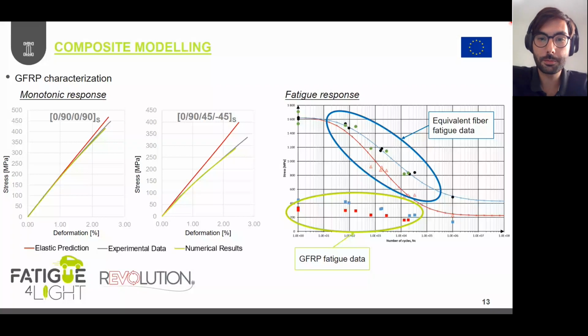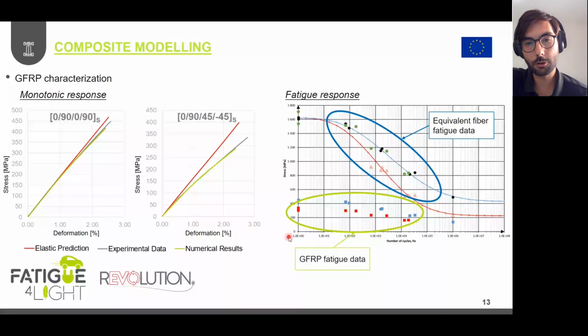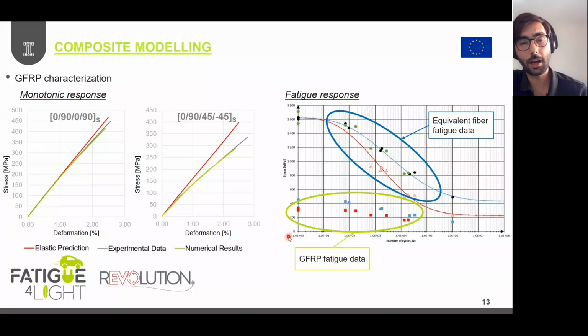Well, up to now, experimentally, we have at the right-hand side chart a few information. For example, the lower part, the glass fiber reinforced polymer fatigue data that we can see comes from experiments, okay? But the reality is that we cannot use this information because the serial parallel rule of mixtures works with component-based information, and this fatigue data is for the whole composite.